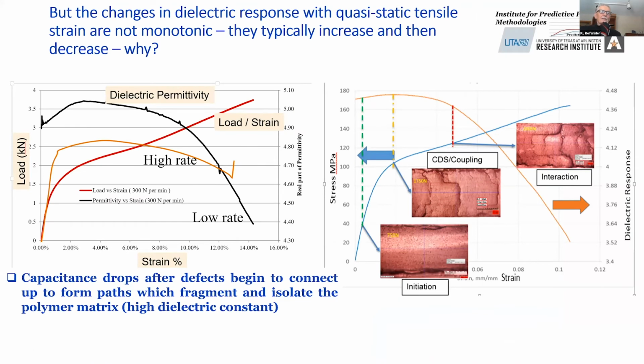Well, there's one more part to this, and we have to approach it carefully. We're back to our diagram on the left-hand side, and superposed on the quasi-static loading diagram on the right are the edge replicas. And we've looked at two stages of this so far. We've looked at the loading, we get some initial defects, and then we start to see coupling when this curve bends over, and that's fine. But there's another final change in the dielectric permittivity that's very abrupt and rapid. And we want to know what that is associated with, this final diagram on the right. So we're looking at capacitance, and we see two changes, not one. It starts out, changes a little, stops going up, starts going down. And then it drops. It drops quite quickly just before failure.